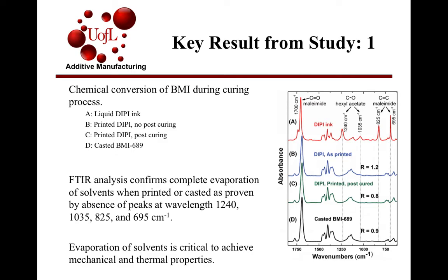So the key point the researchers are looking for here is to understand if the solvents that were used to create the DIPI ink solution fully evaporate during the printing process. And you can see that on the right, the first line there in red is the DIPI ink in liquid form, and there are peaks for the hexyl acetate solution. As you move down to the blue, green, and black lines, those peaks are gone, which means that in the printed and then printed with post-curing, and obviously in the casted BMI, there is no presence of the hexyl acetate solution, which is critical to achieve good mechanical and thermal properties. So the researchers were able to prove that in printing and also in printing with post-curing, the ink fully evaporates.